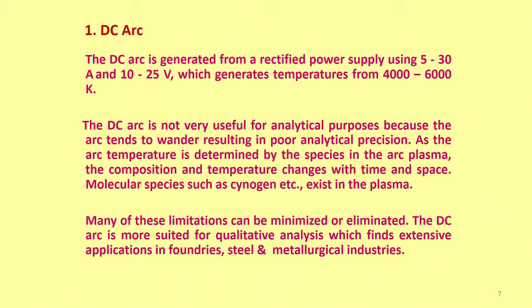As the arc temperature is determined by the species in the arc plasma, the composition and temperature change with time and space. Molecular species such as cyanogen etc. exist in the plasma. Many of these limitations can be minimized or eliminated. The DC arc is more suitable for qualitative analysis, which finds extensive use in the foundries.